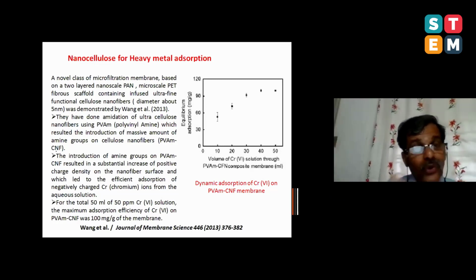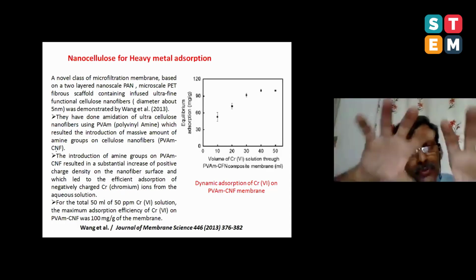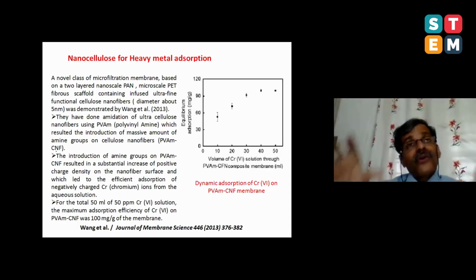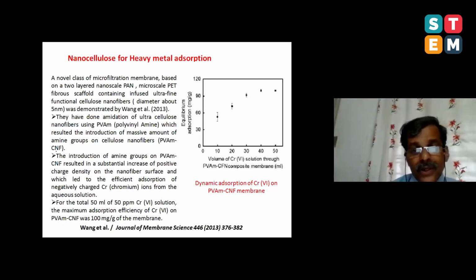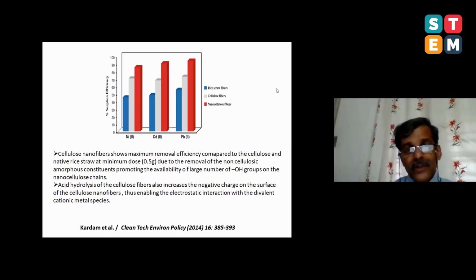For that, you have to do some chemistry on the nanocellulose surface. You treat nanocellulose with polyvinylamine, so then you can put amino groups on the surface of nanocellulose. You have a lot of positive charge on the surface. Therefore, chromium anions could be trapped by this nanocellulose by electrostatic interaction. Look at the equilibrium absorption of chromium by nanocellulose filters. So this chromium could be removed. Similarly, you can remove nickel, cadmium, lead.